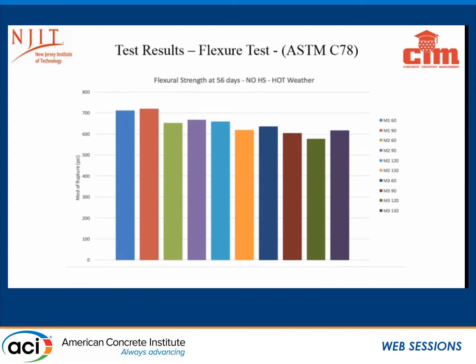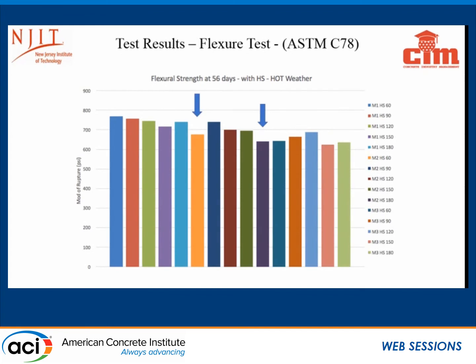And then one of the other tests done was flexural strength. I want to focus a little bit more on mix two. Mix two and mix three, of course, the ones with fly ash and slag, show the most promise in terms of consistency and maintaining all the different characteristics that we're hoping for. Mix two ranges from here, this one is a flexural test, to here. So you see it's fairly consistent over the testing period of 60 minutes down to 180 minutes.